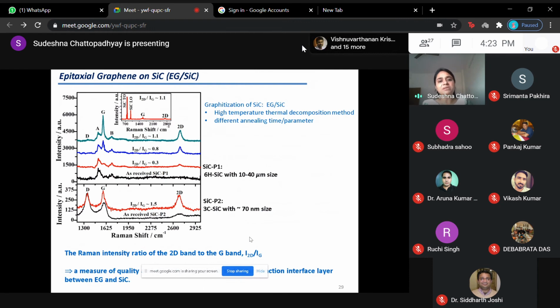So this is the high temperature graphitization we have utilized, and then you can see here the as received silicon carbide. We have chosen two different kinds of polytype: one is 6H silicon carbide, one is 3C silicon carbide. The particle size is also different, to see whether it is really an interface effect, or whether particle size or crystal structure is playing a role, because many parameters are there now. So we have to exclude that. That is why we have shown this.